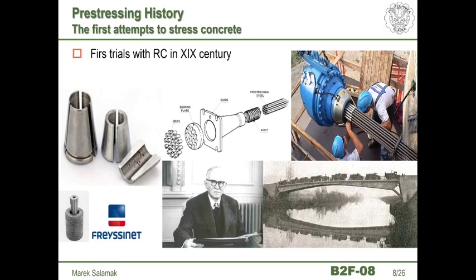The first tensioning experiments appeared together with the first reinforced concrete structures. From the very beginning, engineers tried to pre-stress the reinforced bars, but unfortunately these attempts were very unsuccessful. First, the steel used at the time had insufficient strength and high ductility, so too much force could not be applied. Besides, certain rheological phenomena causing a delayed loss of pre-stressing force were not yet known. Therefore, the first pre-stressed structures collapsed very quickly and were unable to survive even two or three years.